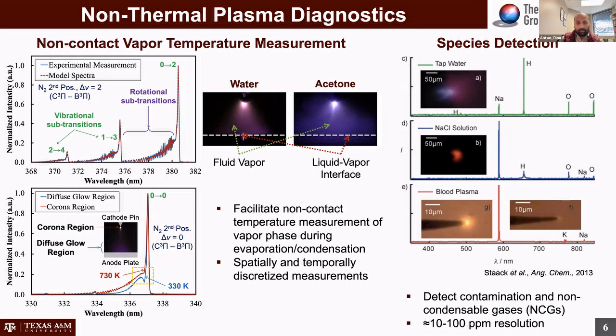And so the hope is to use this technique for species detection on the order of about 10 to 100 ppm, maybe even better than 10 ppm, depending on the type of spectrometer that you have available to you, for measurement of non-condensable gases during phase change heat transfer inside vapors and inside liquids too. So, this is very nascent work. I had a student and he's learning a little bit about plasmas at the moment. And this is ongoing simultaneously along with plasma produced water treatment work.